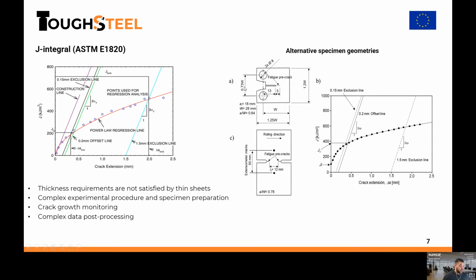For example, you can construct a compact tension specimen, as you can see here, with proportions following the recommendation of alternative standards like ASTM E561, which is less restrictive concerning thickness dependence on the specimen geometry. Actually, it makes no mention of this, so the proportion of the specimen size is not based on the thickness. So you can use this kind of specimen. Alternatively, you can use double-edge notch tension specimens, which are rectangular specimens with 2 symmetrical cracks. Using these alternative specimen geometries, you can use a similar or equivalent procedure to evaluate these J-resistance curves in thin metal sheets.